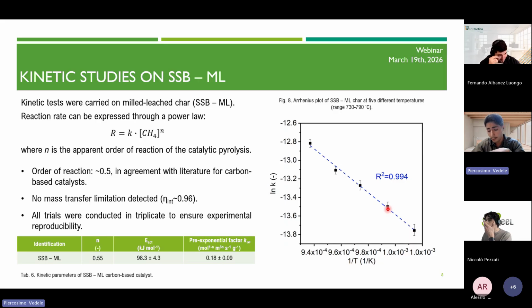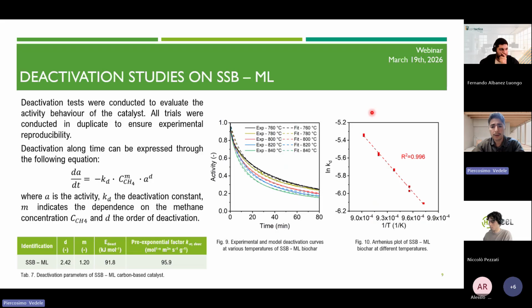And in particular, I want to point out that all the tests were conducted at low temperature for two important reasons. The first is that we want to ensure a gradient-less system, which works mainly in all its length in the same way, and at the same time we want to skip the mass transfer limitation of the system. The same thing was done also for the deactivation studies, which were conducted at low temperature, again to ensure that we are in a kinetic regime.